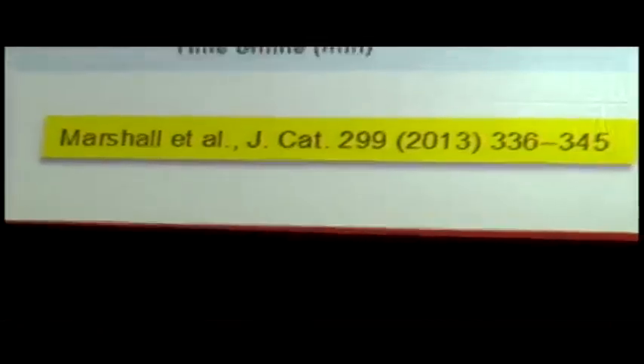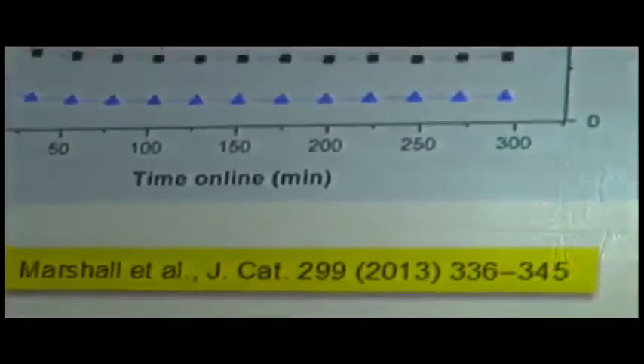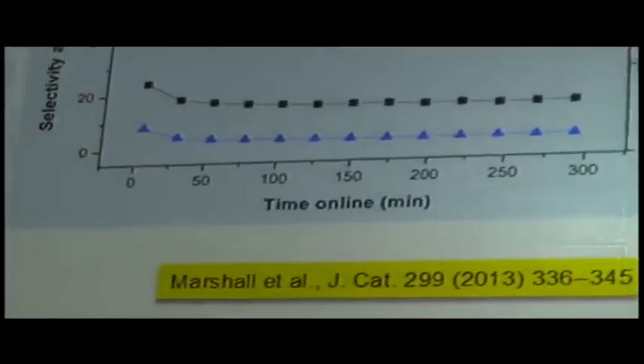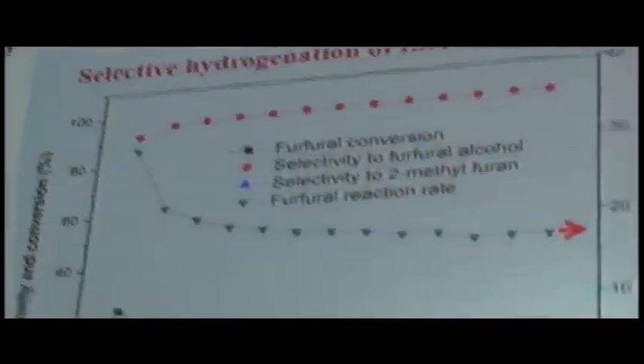So, the reactivity for the catalyst as received is shown here. The important thing to point out is the severe deactivation with just a small amount of time on stream that we see here. We've investigated this extensively in the past, and have shown that the deactivation is due to two components that are going on the catalyst.